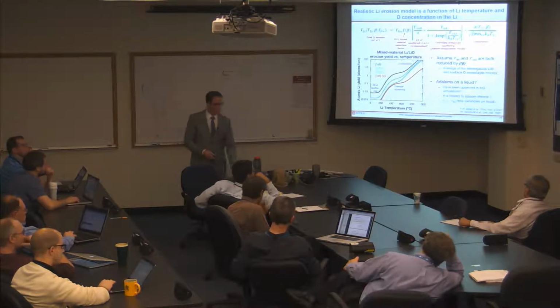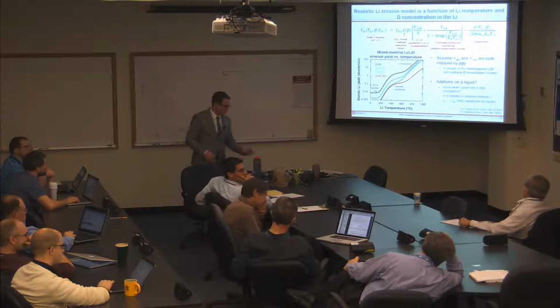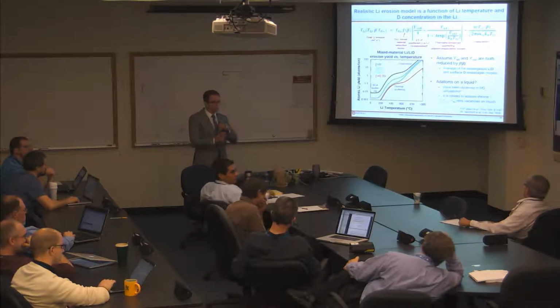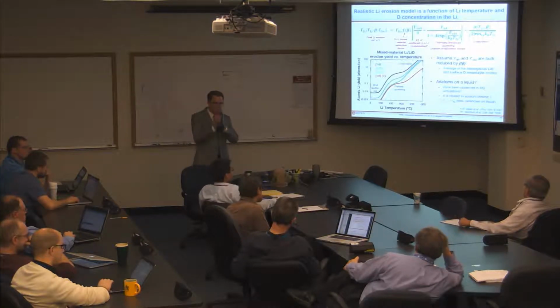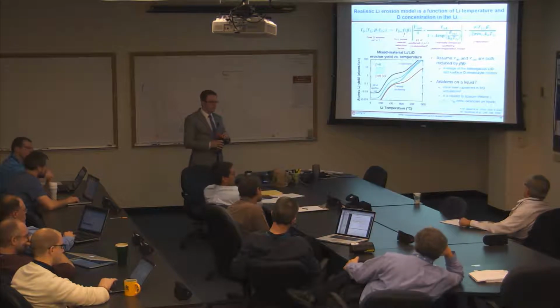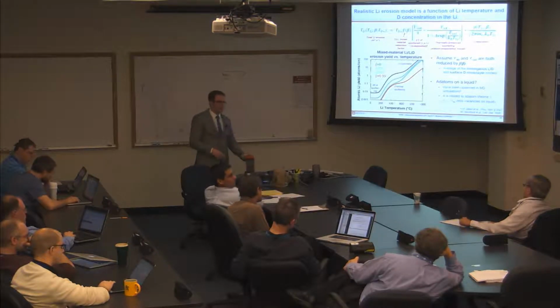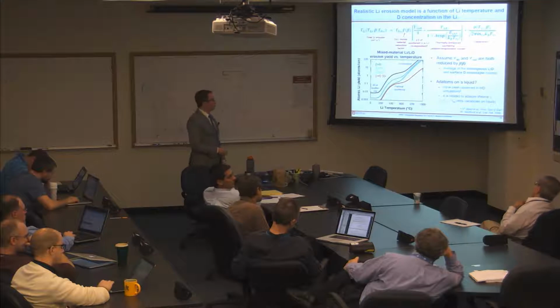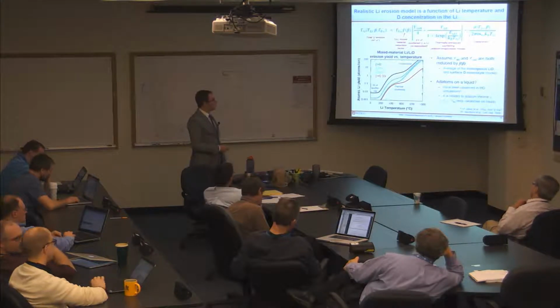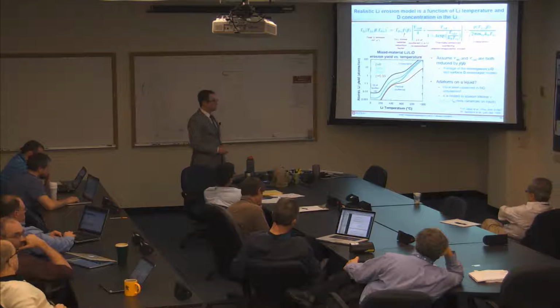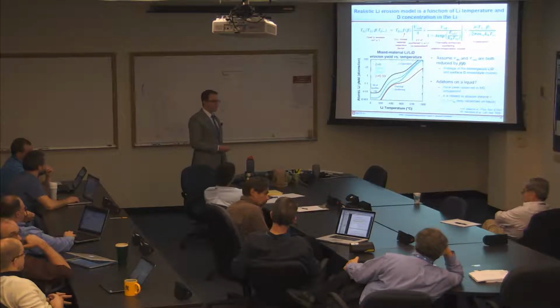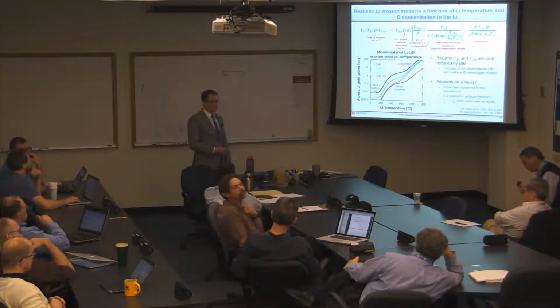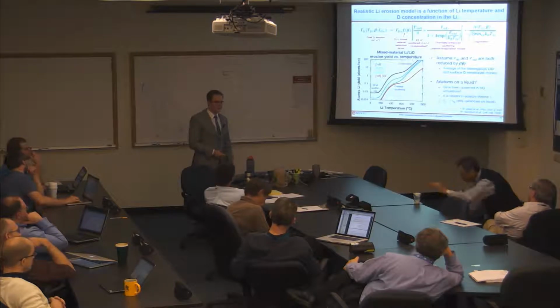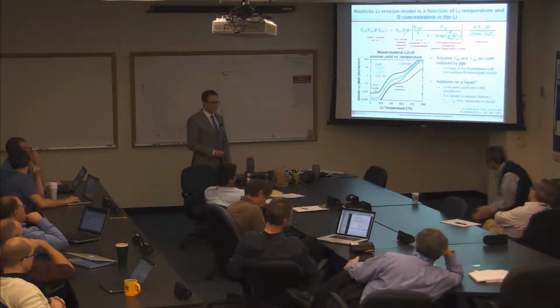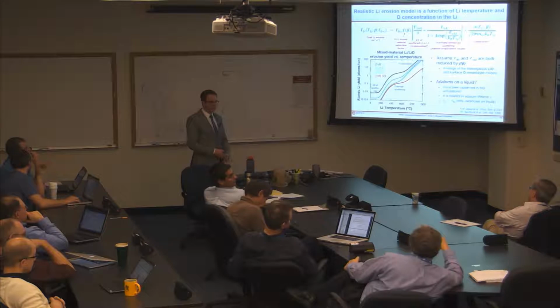For the assumption that all of the lithium that's ionized is returned and deposited on the surface, there's going to be some that actually gets into the plasma, too, maybe small. Well, there's an energy distribution of this sputtered lithium, but it peaks around 1 eV, and if you have sheath potentials that are 10 eV, 20 eV, something like that, there's not really much that's going to get out. Yeah, I agree there's not much.